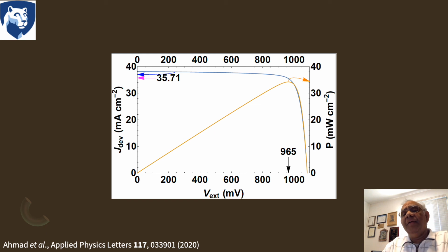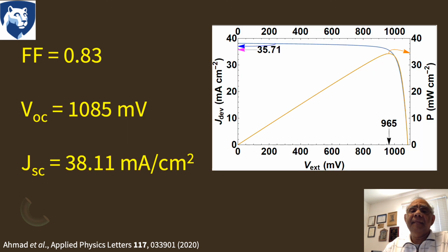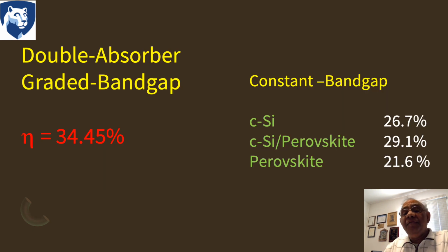The JV curve shows that the fill factor is 0.83, a high value. The open circuit voltage is slightly less than 1.1 volts. The short circuit current density is 38.1 milliamperes per square centimeter. Most importantly, the efficiency is 34.45%. This is a very promising result because the efficiency exceeds the threshold of 30%. That is considered the Rubicon for single junction solar cells.